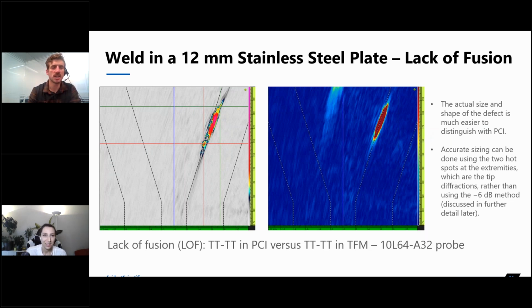So if I can go a bit further into how the color palette was designed, because we did make a specific color palette for this technique. I just picked up this picture because you can see the color palette for TFM and the color palette for PCI at the same time. And what we can see with the TFM is that there's a change in color at 80% and 40%. The reason for that is making it really easy to see the switch from red to green for that minus 6 dB drop that is used for sizing. I'm not even pointing at the right screen, sorry. So from 80% to 40%, we can use that drop to make it easier to see the change from minus 6 dBs for sizing.